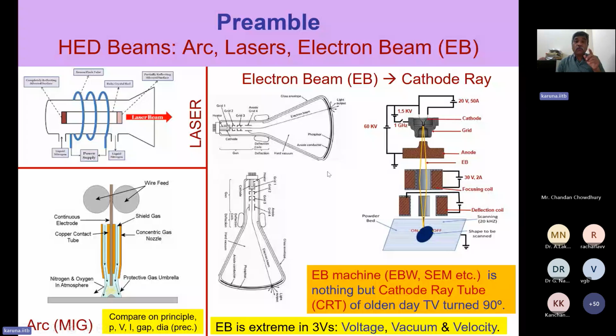Okay, so it's not just the velocity, it is the acceleration which is also important. In the case of arc, your acceleration will be 0.5 meter per second square. In the case of laser, it can go up to 8,000 meter per second square. Whereas here it is close to infinity because velocity itself is 1 lakh meter per second. So acceleration will be much higher than that. So that is making it attractive. But then there's a huge negative side.